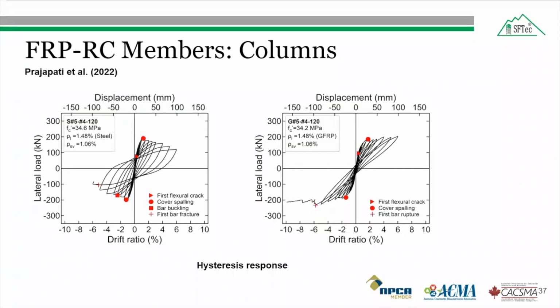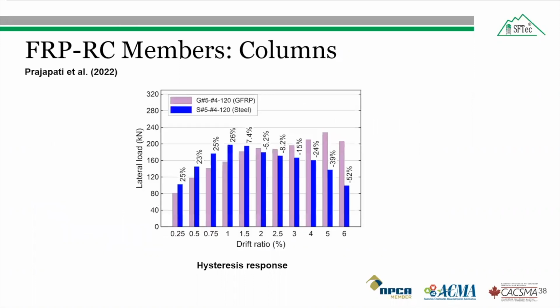The lateral strength in the hybrid reinforced concrete column increases until severe concrete cover spalling and starts to degrade thereafter, which was opposite to what was observed in the glass fiber reinforced polymer reinforced column, where the lateral strength increased until the failure of the column. Due to the higher stiffness of the steel bar than the glass fiber reinforced polymer bar, the lateral load was more in the initial drift cycles, but after 1.5% drift ratio, it reversed, because of the concrete cover deterioration, and more lateral load was absorbed in the glass fiber reinforced polymer concrete column. Finally, the GFRP reinforced concrete column attained more lateral load than the hybrid reinforced concrete column.